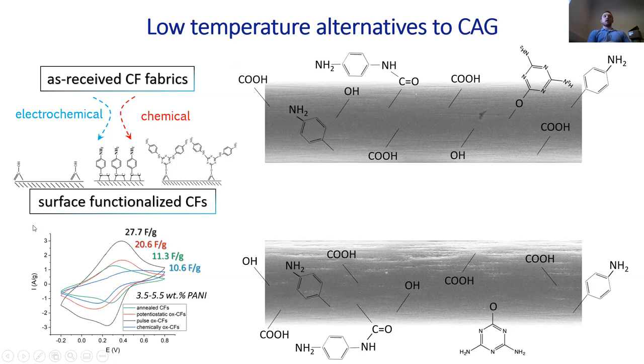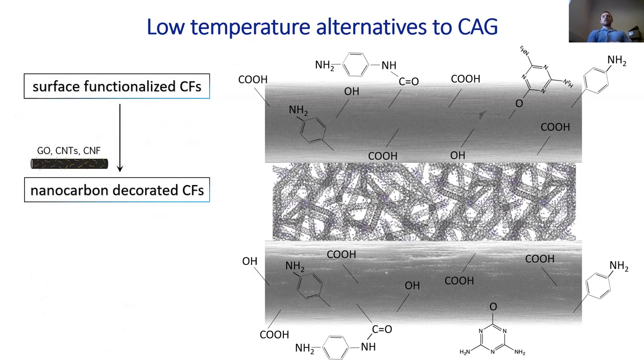So in this case, for example, the first attempt I was exploring is the simple oxidation of carbon fibers, which makes them hydrophilic and improves adhesion of, for example, conducting polymers deposited on top of the carbon fibers. So I've tried different electrochemical functionalization methods with the further deposition of polyaniline on top of the carbon fibers. We showed that the larger area and better electrochemical performance was achieved for pulse oxidized carbon fibers, leading to more uniform distribution of functional groups on the surface of carbon fibers, and as a result, more uniform and thin coating of conducting polymers.